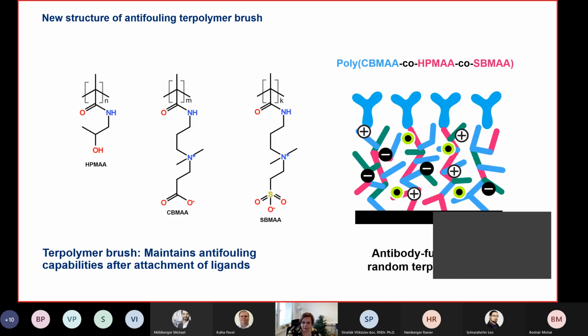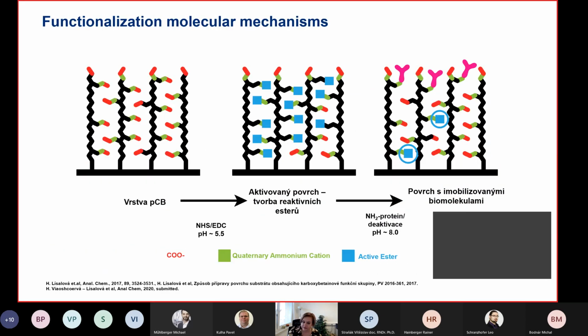Here is the design of our newly developed terpolymer brush. It's composed of three monomers, three types of monomers. Each monomer has a certain role in the final architecture, and very important is also the ratio and the surface ratio of the coating. And what is a great advantage of this antifouling brush is that it maintains the super antifouling capability even after immobilization of biorecognition elements like antibodies onto coatings, even with very high loading density. Therefore, it's very interesting for biosensors. And I will show you then examples in which we use this terpolymer brush. We have recently patented this structure.